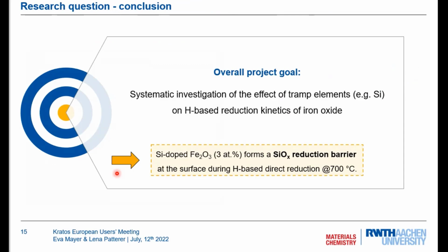And coming back to the research question we defined in the beginning, so when we did the study of silicon and the influence on the hydrogen-based reduction kinetics, we can say that it has a negative influence. So we form the silicon oxide reduction barrier at the surface when we have this treatment of high hydrogen-based direct reduction at 700 degrees C.